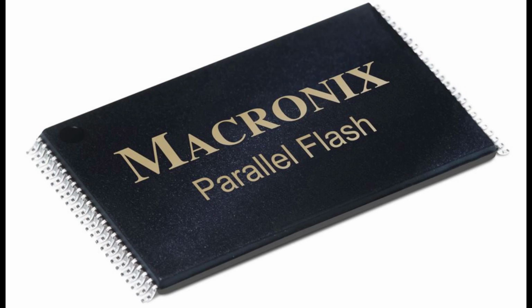Endurance also decreases with the number of bits in a cell. With more bits in a cell, the number of possible states, each represented by a different voltage level, in a cell increases and is more sensitive to the voltages used for programming. Voltages may be adjusted to compensate for degradation of the silicon oxide, and as the number of bits increases, the number of possible states also increases, and thus the cell is less tolerant of adjustments to programming voltages, because there is less space between the voltage levels that define each state in a cell.